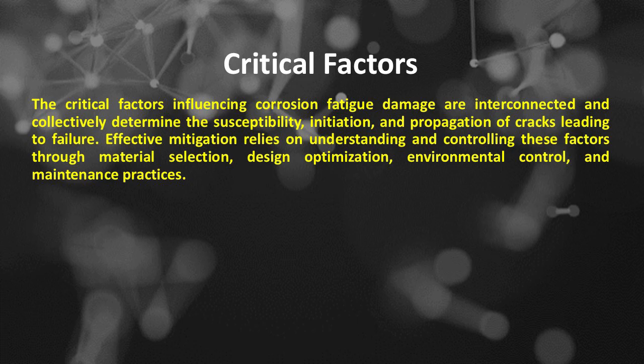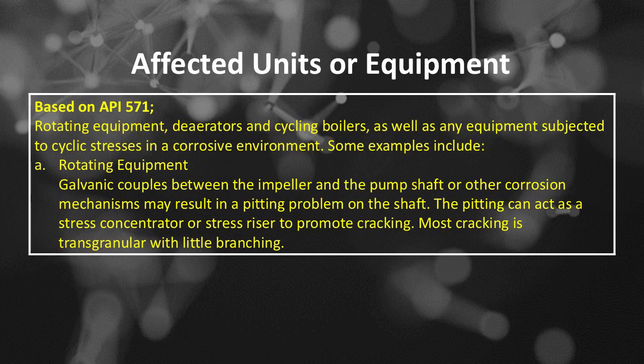Corrosion fatigue damage affected units or equipment based on API 571: rotating equipment, deaerators and cycling boilers, as well as any equipment subjected to cyclic stresses in a corrosive environment. Some examples include, Number A, rotating equipment. Galvanic couples between the impeller and the pump shaft or other corrosion mechanisms may result in a pitting problem on the shaft. The pitting can act as a stress concentrator or stress riser to promote cracking. Most cracking is transgranular with little branching.